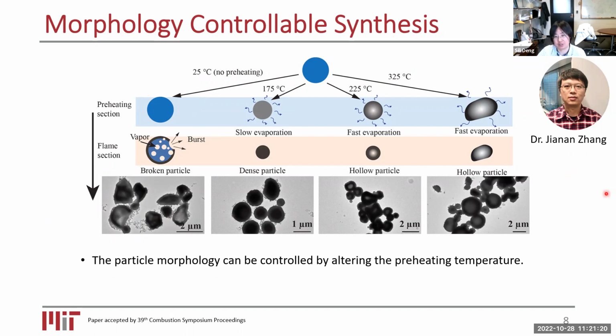Okay, at a very high preheating temperature, we could get some spherical particles, but first the size distribution isn't very uniform. And from the contrast, you could probably also see that the particles are hollow. And somewhere in between, we see this transition from dense, spherical, relatively uniform particles to the hollow structure, by controlling the preheating section, meaning controlling the temperature history of the particles. So definitely the conclusion here is that the temperature history that the precursor experienced definitely influences the morphology.